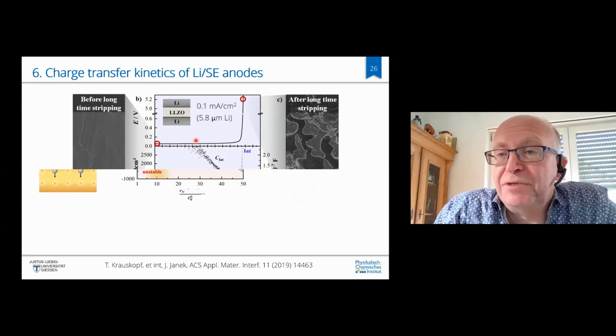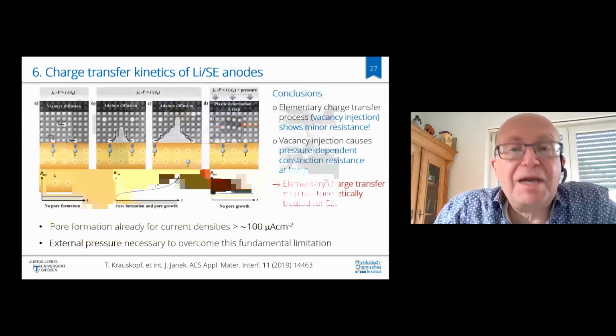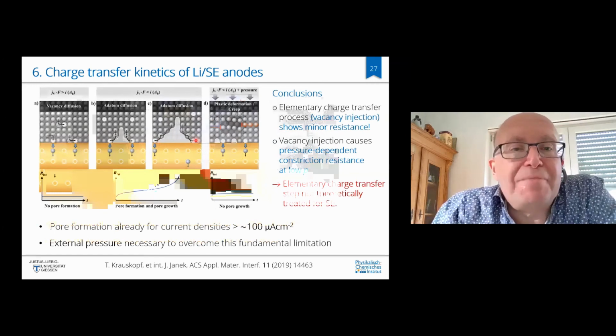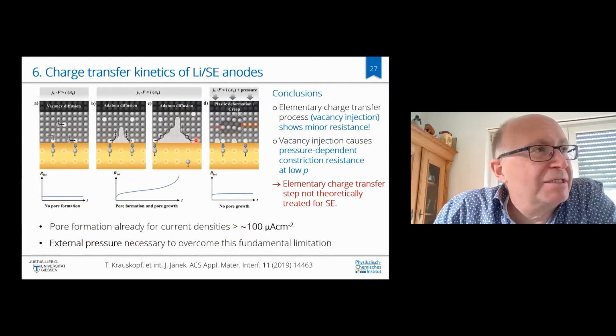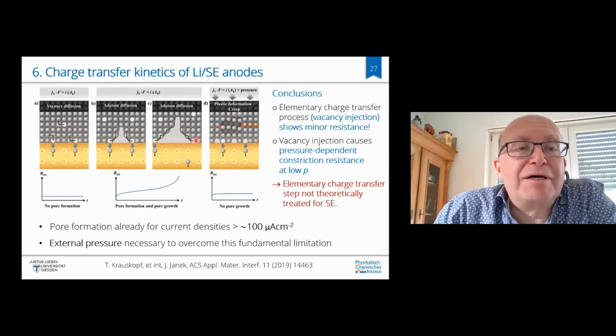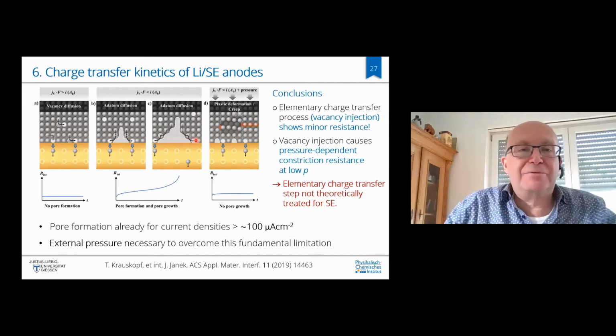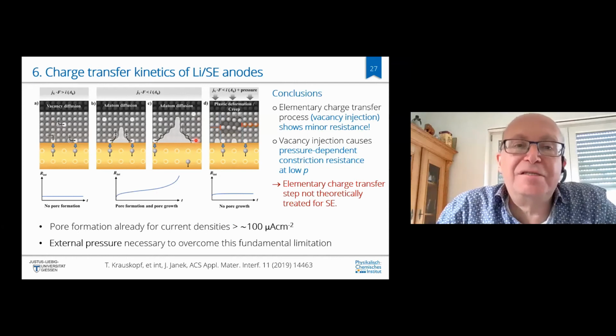Because in practical applications, in order to be competitive, we need, of course, current densities in the order of a few milliamp per square centimeter. And this is something which I think is still not, at least to me, not possible. I think there is quite some announcement of QuantumScape. You may know that, but they may have found a solution for an anode-free cell where a lithium metal anode may be cycled well enough at high enough current densities, but I think this is still to be communicated.